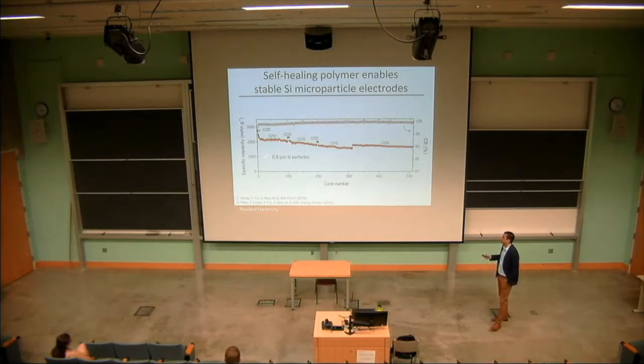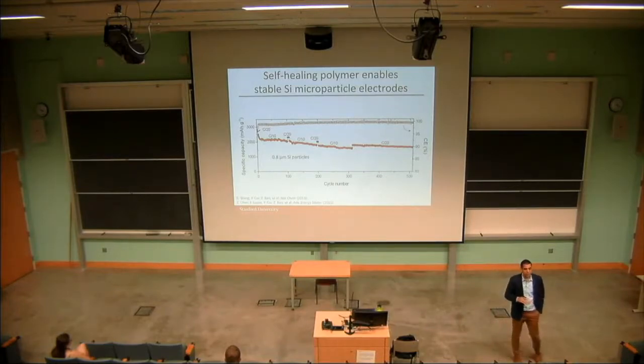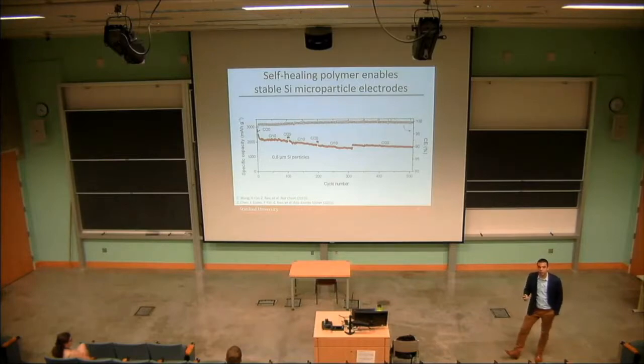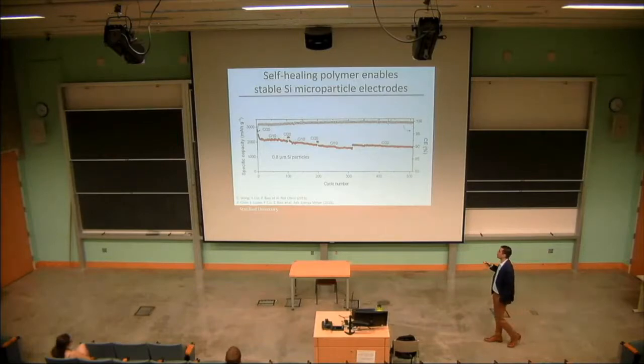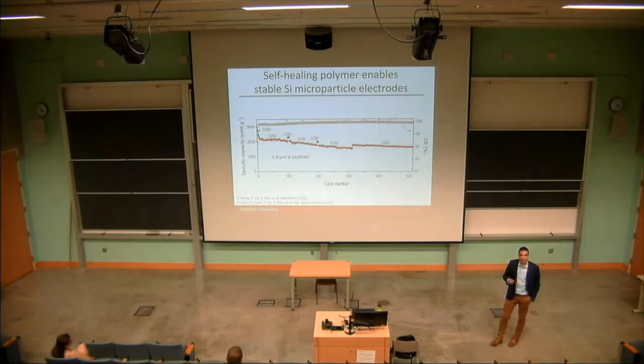And we're able to cycle these very large silicon particles. You'll remember I mentioned earlier that 150 nanometers is kind of a critical dimension for silicon to have stable cycling. But you would really like to have very large particles because they're much cheaper to buy, much easier to put into these electrodes. And so we were able to, for the first time, really show successful long-term stable cycling with micron-sized particles using the self-healing binder concept.